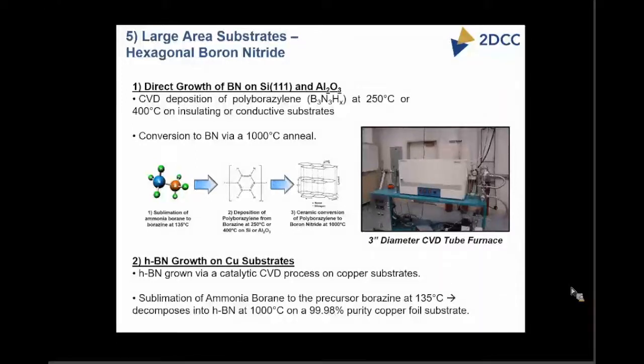And we wanted to make sure, since Joan Redwing was very interested, to have this be available as a material that could be supplied to use in conjunction with other types of growth or deposition or transfer processes. Also, you can grow this by direct deposition on copper substrates and then do a transfer just like you would with CVD graphene. So this capability exists, and if there's any interest in substrates based on these materials, they could be provided through the 2DCC.